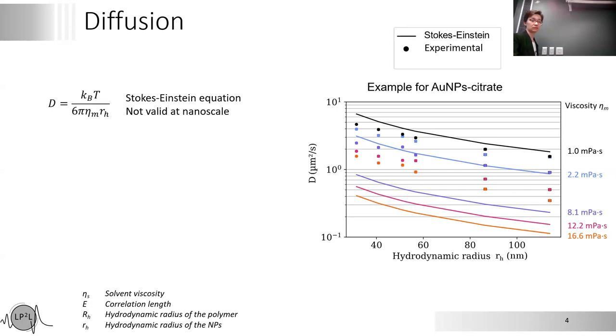It can be explained pretty easily because the macroscopic viscosity is determined at macro scale, not nano scale. And the condition to use Stokes-Einstein is that the particle we are tracking should be way bigger than the molecules of our solvent dispersion medium. Here it's not the case with our polymer, which is more or less the same size as our nanoparticles. So to overcome this issue, people in the literature introduce an effective viscosity. And the question is how we can model this effective viscosity to have an equation to determine the diffusion coefficient.